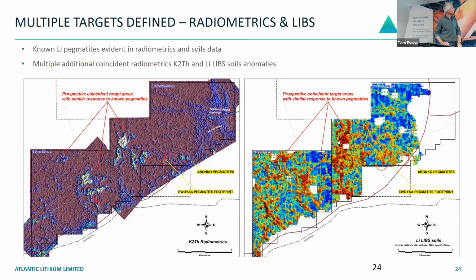But back to the LIBS here. So we've tried to understand these levels. The blues would probably be around 0 to 100 ppm in soils through the LIBS. And then the greens around 100 or 150 to 300 ppm. And then when you're on the pegmatites here, you're between 300 to 600, 700 ppm in soils. But this particular feature here, the Afrangwa granitoid and the Ekrabadzi granitoid here, they're sitting around 1,500 up to 9,000 ppm in soils. We've assayed rock chips, but we don't repeat those values.